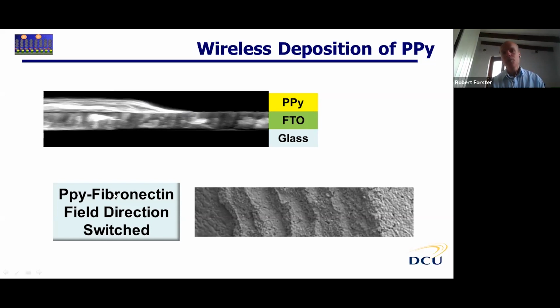One of the things we showed you from Chunyan's data is that you can swap the polarity of the electrodes - one electrode that's initially positive and the other negative, you can cross those over and switch the direction of the polarity, and that will cause the film structure to change. So that's what we've done here. Just to confuse things, this is the positive end, this is the negative end, but what we're doing is swapping during the deposition, pulsing back and forth. What happens then is you get a combination of deposition kinetics and mass transport.